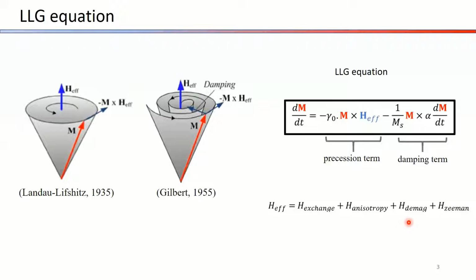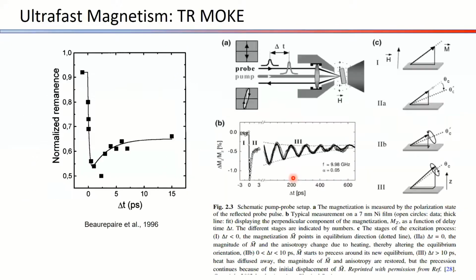The largest contribution to the effective magnetic field is provided by the demagnetization fields, which are responsible for the domain structure formation in the magnetic material, because the demagnetization energy will be minimized by creating domains. So they are very important. And here is the Zeeman energy. Here, Zeeman energy is the potential energy of the magnetized body in an external magnetic field.